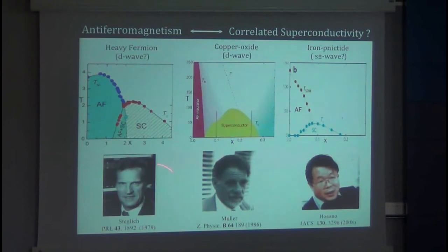If we go back in time, originally in the late 70s, it was found that when antiferromagnetism is suppressed in heavy fermion superconductors, the superconductivity appears. Then in the late 80s, Alex Müller found that when antiferromagnetism is suppressed in the cuprates, superconductivity appears. Hosono-san found just 10 years ago that when antiferromagnetism is suppressed in the iron superconductors, superconductivity appears. There's an a priori reason to ask whether we can find a direct link between strong antiferromagnetism and correlated superconductivity.